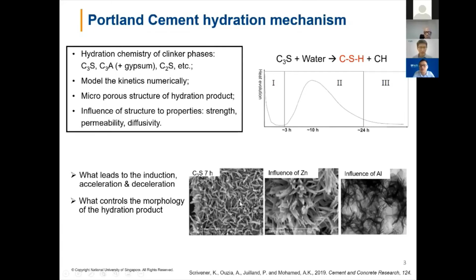If we look at the hydration product, the CSH of the pure C3S, we see a lot of fine needles as the hydration product at about 7 hours. However, if we dope the element zinc into C3S, we end up with needle-like hydration product, but much bigger, much thicker and much longer. If we have aluminium in the hydration product, the CSH growth changes from this one-dimensional growth to two-dimensional growth, not into needles, but into foils, into sheets, okay?